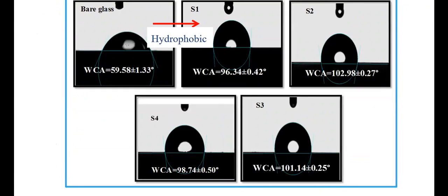Now for the binder system with PDMS and Sylgard, as we increase the Sylgard ratio into the PDMS, for the bare glass, you can see the water contact angle is about 59, I would say about 60 degrees. When we introduce the coating system with PDMS and Sylgard together, the water contact angle tends to increase and the hydrophobicity tends to increase. As the Sylgard ratio increases from S1 to S2, the contact angle increases, then it starts to decrease back. That means it goes up and comes down.